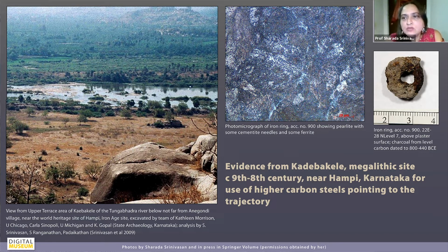And if you look at low carbon wrought iron, it's a completely different structure. We just mainly see the ferrite phase. So you'd have to look at that to believe me. But this is a higher carbon steel. So it seems that this was already being experimented with, and that's what would have resulted in the wootz composition.